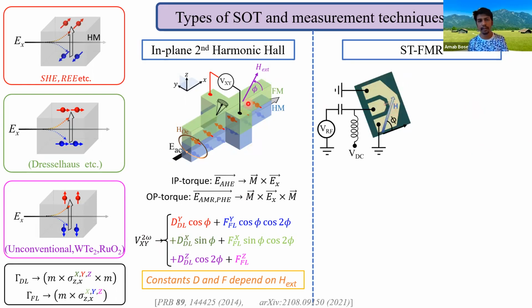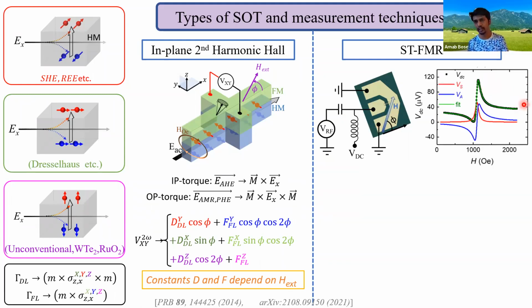For the STFMR, again, we have heavy metal ferromagnet bilayers, but we pattern it to a rectangular shape as shown here. And we make contacts of coplanar waveguide shape such that it can carry microwave current. So we run a radio frequency or microwave current in the system, measure DC voltage using a bias T, while sweeping the external magnetic field at an angle phi with respect to the current flow direction. Due to various current-induced torques, the magnetization rotates, and here the resistance varies due to anisotropic magnetoresistance. Now, oscillatory resistance and oscillatory current together mix up to produce DC voltage, and we can measure very large DC voltage at resonance as shown here.